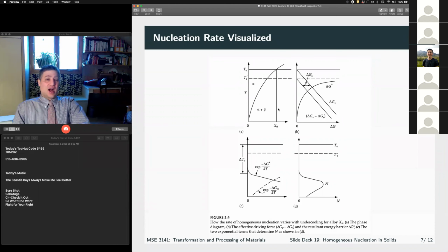Thermodynamics says, if I hold here, I'm going to go to alpha and beta. And yes, that's true. If I hold it for geological timescales or universal, astronomical timescales, that is true. But over the course of the lifespan of the part that my material is made out of, I'm going to stay at where I am. I'm going to stay at pure alpha if I just quench down to room temperature, because I don't have sufficient atomic mobility to form my secondary phase.